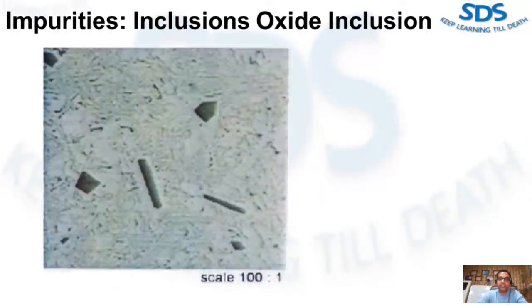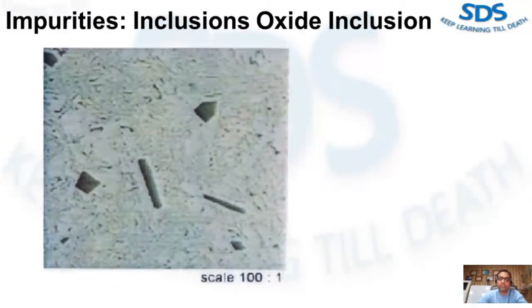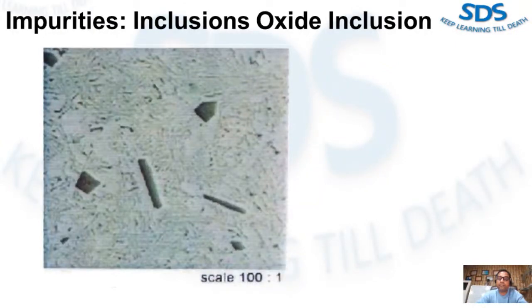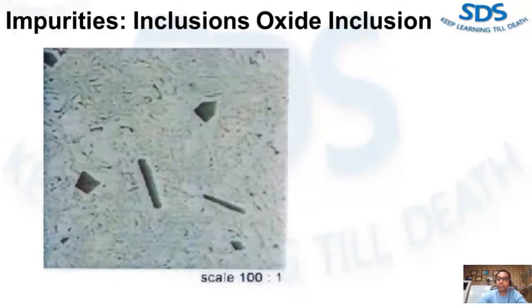Inclusions present in a melt and in subsequent die cast products have many detrimental effects. Inclusions are an impediment to metal flow; in extreme cases they can result in lack of fill in the die cavity, especially in thin sections. Inclusions have a negative effect on mechanical properties, resulting in lower yield and tensile strength, elongation, and impact resistance. Many inclusions are quite hard and impair machinability. Surface inclusions impact finishing operations such as plating, painting, and anodizing. Inclusions are preferential sites for nucleating hydrogen porosity.